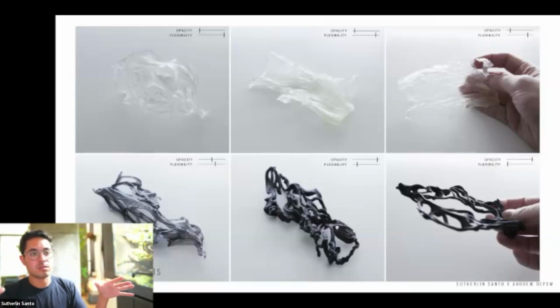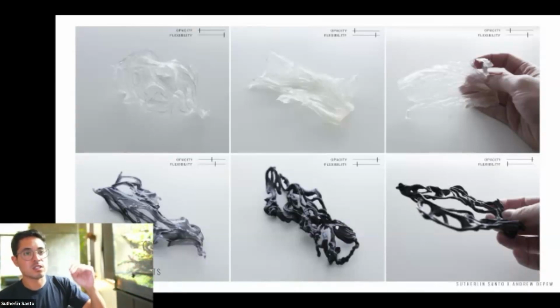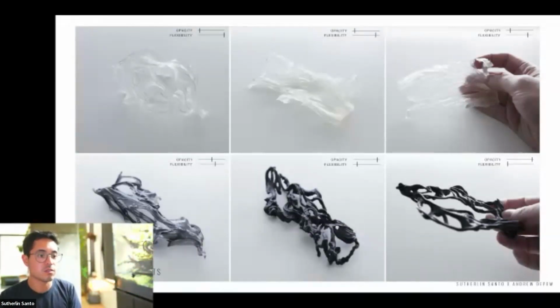So funny thing, we should add this in before we send this out to everyone. Your samples shrink generally. Until you find the right aggregate, samples will shrink. Part of the reason we like fibers is because the fibers cross, and instead of shrinking and getting smaller, it shrinks and gets flatter. So you're also going to notice that as you explore different kinds of additives, the way the material sets up is going to be different than just the base biopolymer itself drying.